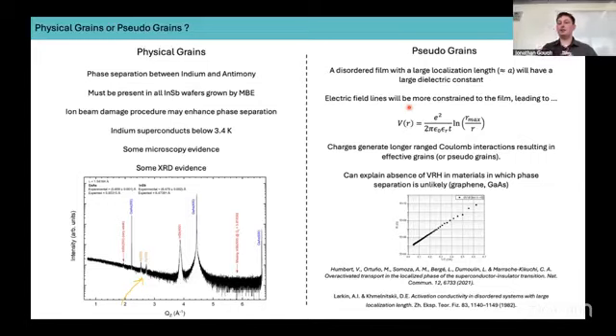very large localization length. In these systems, the electrons are slightly more mobile because they behave more like a metal, say, which effectively screen the electron-electron interactions, giving it this long-range character. It's got this additional logarithmic term. So these longer-range Coulomb interactions can be modeled as effective grains or pseudo-grains.